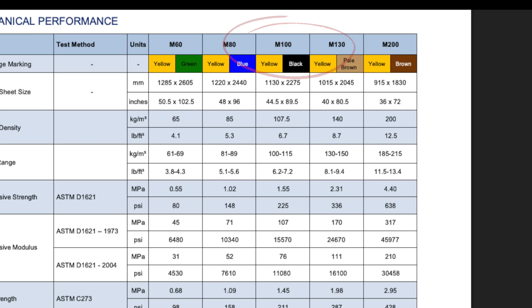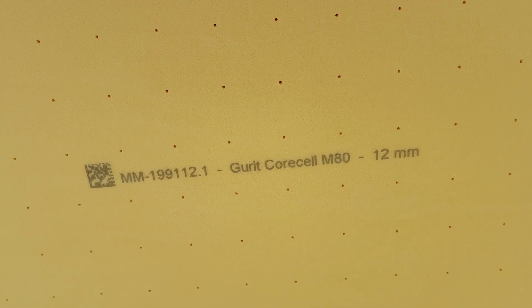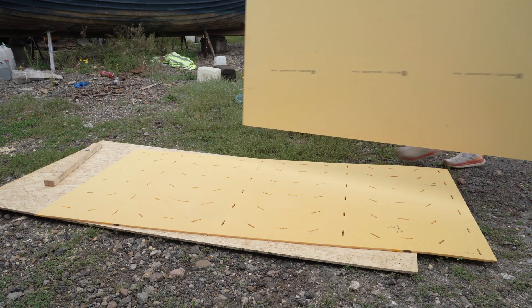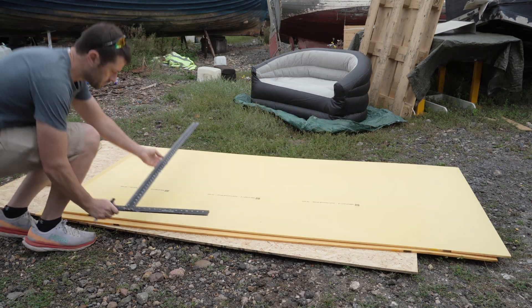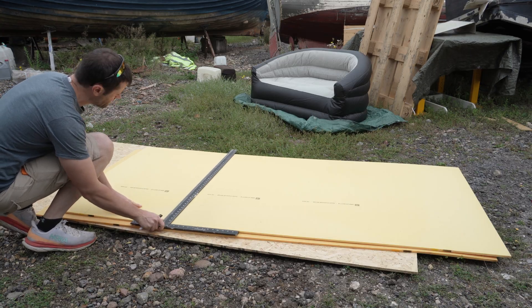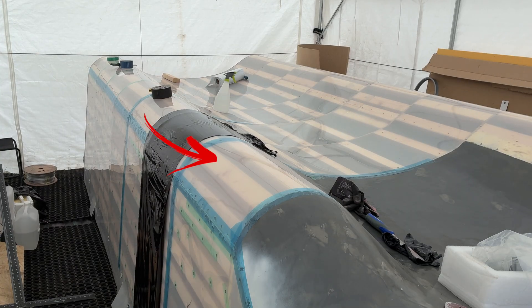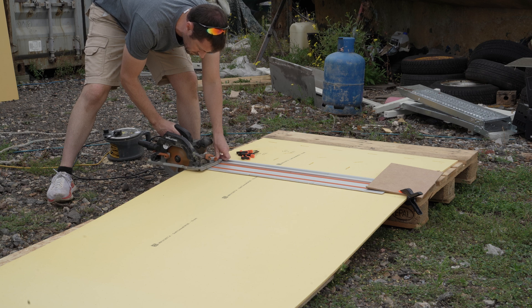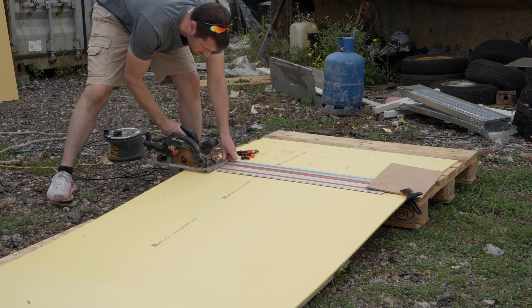For the bottom and the shaped scoops on the mould — the cylinder-like rails at the top — I've gone for 100kg per cubic metre density and 10mm thick. These sections are the most curved and so will naturally resist bending, but I've chosen this fairly high density for resisting compression. For the sides and possibly the back, which are flatter, I've gone for a slightly thicker core to help stiffness, but a normal density of 80kg per cubic metre. It turns out from the spec sheets that in practice you get a little bit more density than expected, so M80 is usually an average of 85kg per cubic metre. The sides do not go all the way to the bottom of the mould — you don't want your core reaching all the way to the edges of your laminates, as they are vulnerable to damage and hard to bolt things to. Instead, I'll taper the core down and have a solid laminate for the edges.